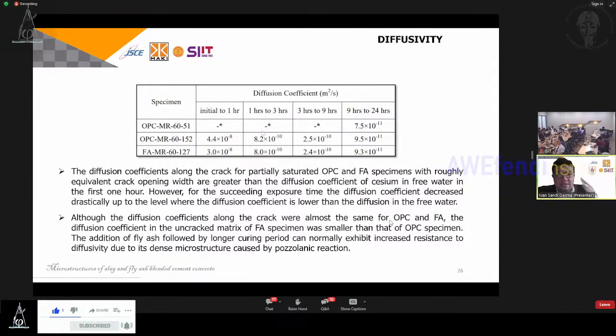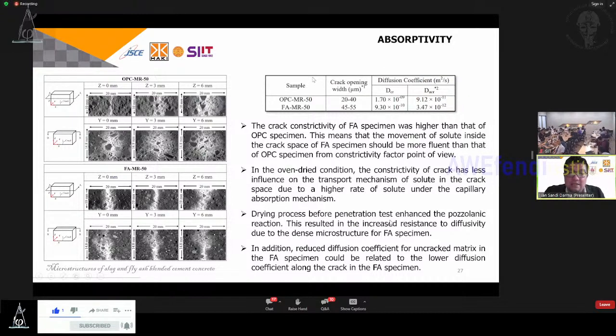And then for the last in my presentation, the absorptivity test. This is from a flexural tensile, the crack was generated by flexural load. And then as you can see here, for the OPC, the tracer spreads out into the specimen, not only in the crack, but also the uncracked matrix. But for the fly ash, as you can see, the spread is smaller compared to the OPC. Here, we can conclude that in addition, the reduction of diffusion coefficient for uncracked matrix in fly ash specimen could be related to the lower diffusion coefficient along the crack.